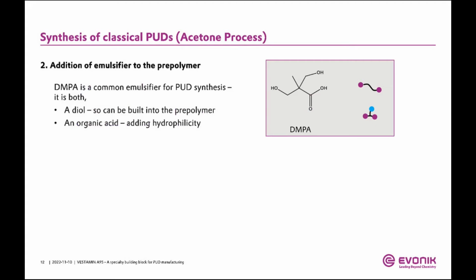Then, of course, when we want to later on bring our polymer into water and disperse it into water, we have to make it more hydrophilic. And this is why we have to add some emulsifier to the prepolymer. The most commonly used emulsifier nowadays, I would say, is the DMPA, dimethylolpropionic acid, which has an acid function where we incorporate the hydrophilicity into the system, and it is also a diol. So that means the diol function acts kind of like a resin. It's a very short diol. It's not a long chain resin. So we can see here in this schematic picture on the lower right, we have a very short chain, which then can also react with the isocyanate.